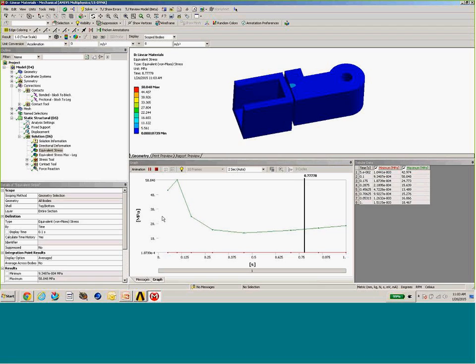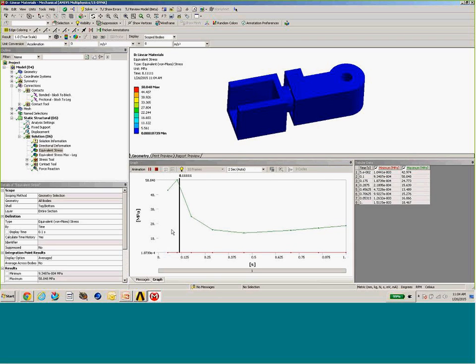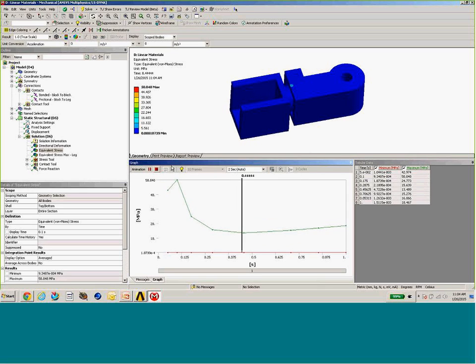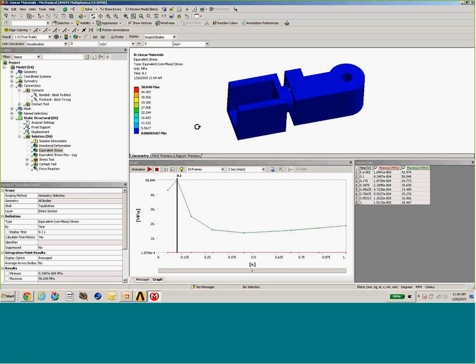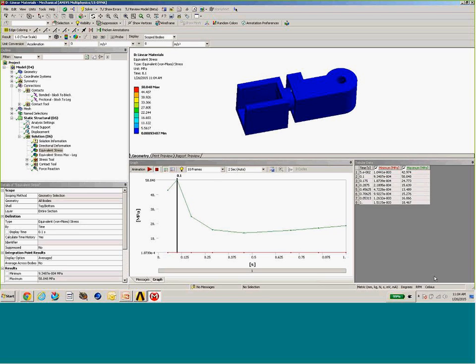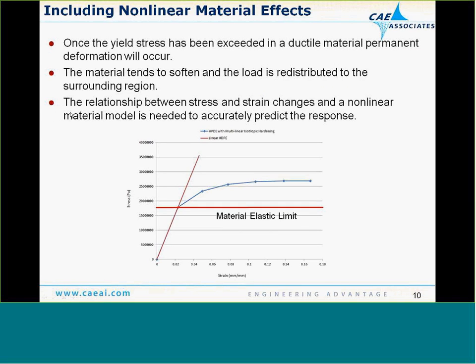As we can see from the animation, as the parts are pressed together, we get a very high initial stress when the contact is introduced. The elastic limit for this material is around 18 megapascals, and we can see stresses above that quantity. Here's where we need to be careful: we've defined our material model as linear, so the finite element program is calculating the relationship between stress and strain using that linear modulus regardless of the stress induced. Any stresses that occur above the elastic limit are completely false, so we need another way to determine what's happening to the part beyond that elastic limit.